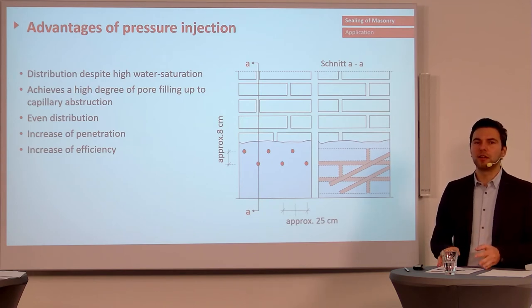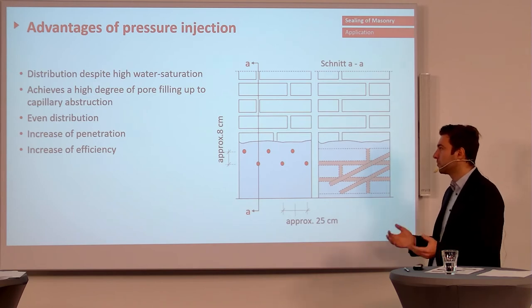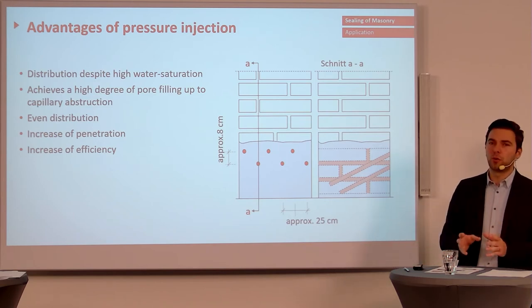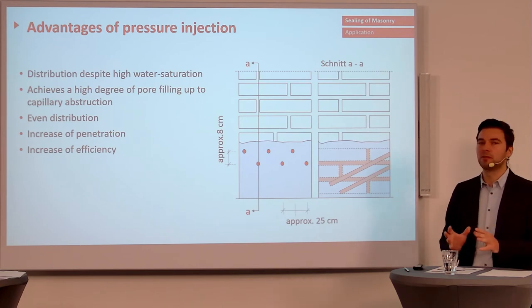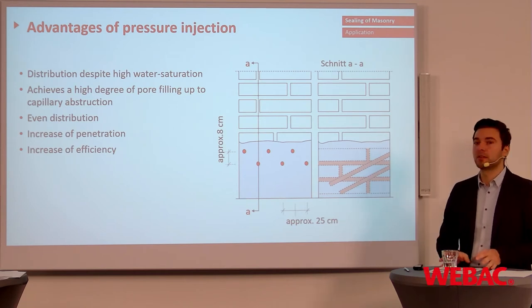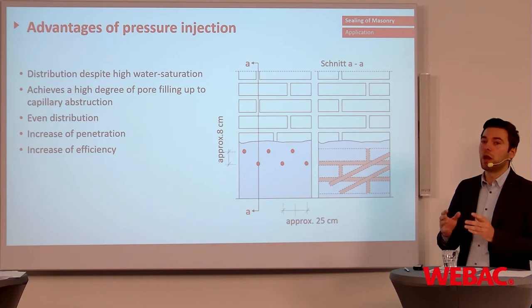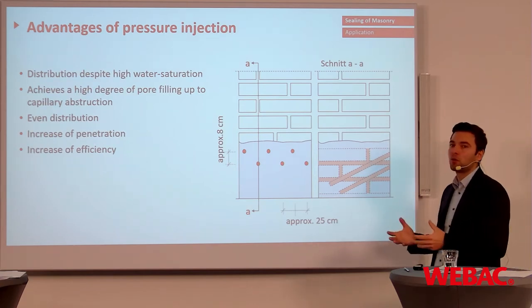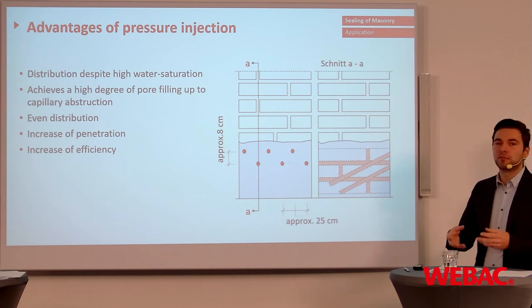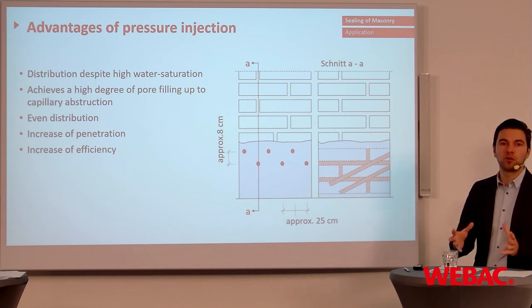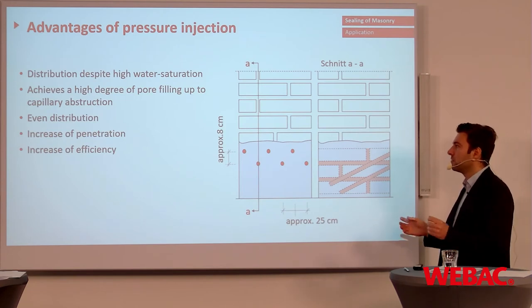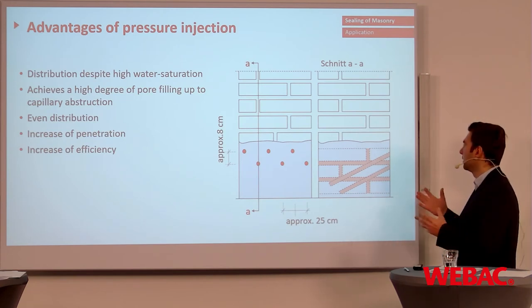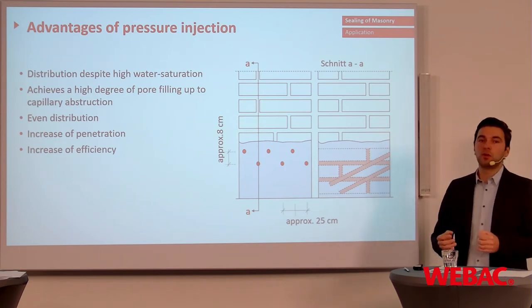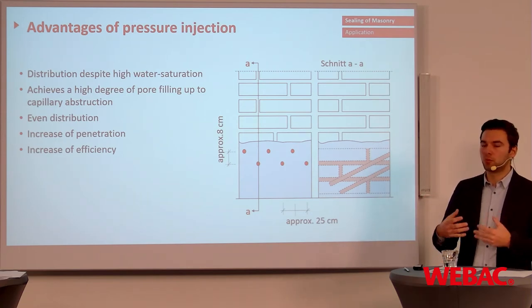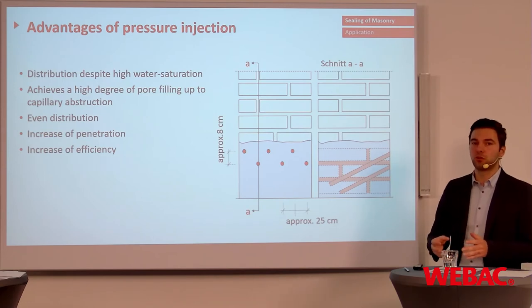It also achieves a high degree of pore filling up to capillary obstruction, meaning the small cracks and fissures in the mortar joints are completely filled with the injection material, and due to its properties as a long-lasting sealing, you have a watertight structure, without any further influence of water moisture on your construction. You have an even distribution inside the masonry. You are increasing your penetration due to the pressure, and for sure this is also increasing your efficiency.